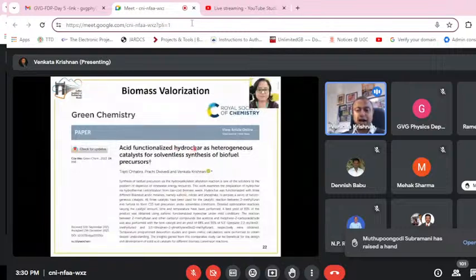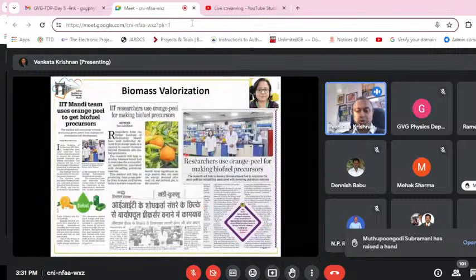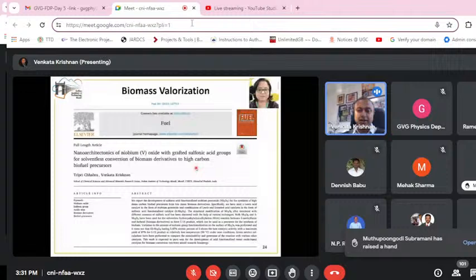In yet another work, we have taken hydrochar, obtained from waste orange peels, and functionalized it with different functional groups like sulfonic, nitrate, and phosphate groups to get a heterogeneous catalyst. That catalyst was used for the solventless synthesis of biofuel precursors, and this work was also published in Green Chemistry Journal in 2022, and it got some media attention during the time of its publication. Quite recently, in the beginning of this year, we published another article in the journal Fuel, wherein we took niobium pentoxide and grafted it with sulfonic acid groups and used it for the solventless conversion of biomass derivatives to high carbon biofuel precursors.